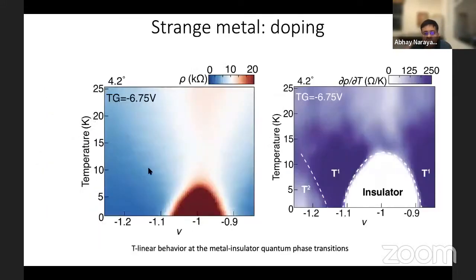So let me first show you some data that is taken along the density axis. So here is the half filling point. Sorry, it's written as -1 in this notation, but that's the half filling point. And as I tune the density, I have 2 metal to insulator transitions that happen here. And this is showing you what the temperature dependence of the longitudinal resistance does.